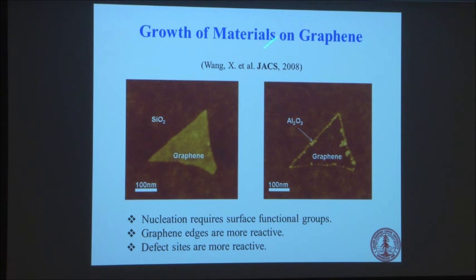A long time ago, actually, we were doing a lot of electronic device work. And for example, we have a graphene here, and we try to put a dielectric material on top so that we can put on gates and do electrical measurements. But what we found is that these films, let's say the dielectric film here, aluminum oxide, it doesn't really like to grow on the graphene, because graphene is such an inert structure. But they go to the edges. Okay, so that means the edges are actually chemically reactive, and you can grow stuff from these defect sites.